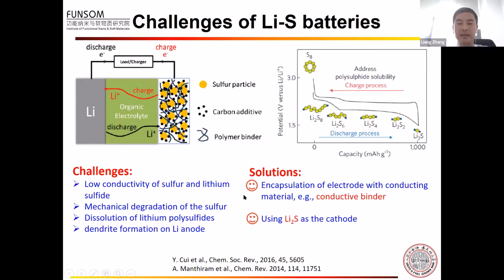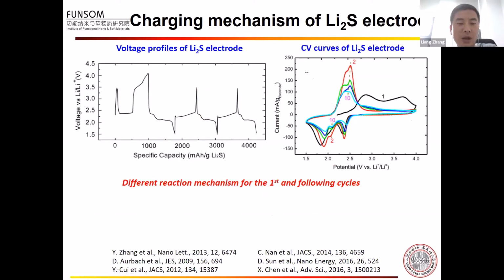And during the past more than 10 years, people have developed different methods to overcome these challenges. So, for example, we can encapsulate the electrode with a conductive material such as a conductive binder. We can also use lithium sulfide as a cathode, because lithium sulfide is fully lithiated, it's not necessary to use lithium metal as an anode anymore. We can use some other anode material such as silicon, tin, and even carbon. However, when we use lithium sulfide as a cathode material for lithium-sulfur batteries, we always need to set a very high cutoff voltage for the first charge process.